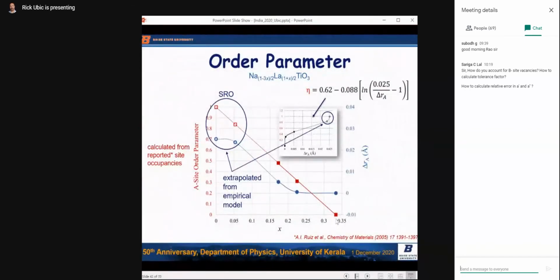And in interest of time, I'm going to start to speed up a little bit. You've got an ordering parameter, which is a line. You might not be surprised. It's a linear ordering parameter. When X equals 0, you get the perfect order, and X equals 1/3, you get 0 order. And we can do a curve fit for that, right? So whatever RA correction you need to put in, stuff that in this equation, it tells you what the ordering parameter is, right? So that was kind of cool.